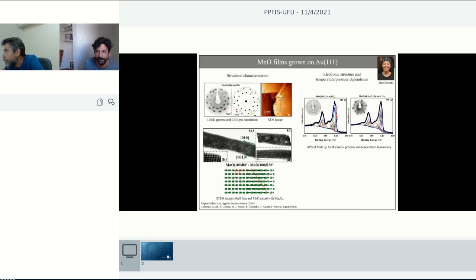X-ray photoelectron spectroscopy. And from this peak analysis that you see here, that's pretty extensive, we can judge how much of the type of defects we have in these oxide films, because we know from these peak ratios here the amount of manganese with low coordinated sites. So this is the work that Chad has been performing and analyzing.